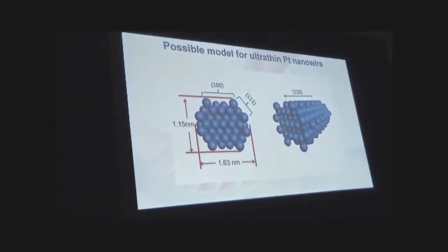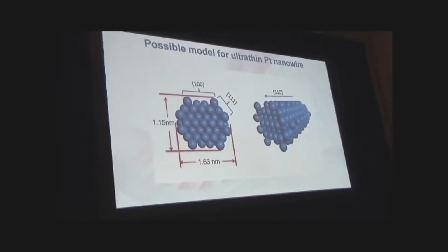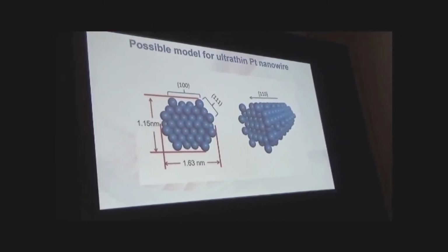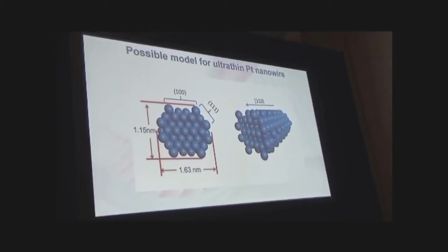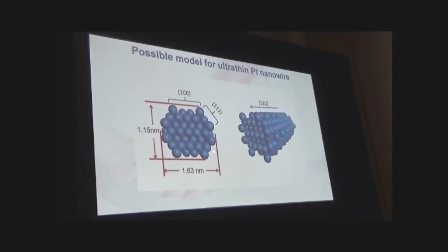Here is the model of the ultrathin Pt nanowire. Because, experimentally, the diameter of the Pt nanowire is about 1 nm, we can construct a reliable model. If you synthesize a nanowire of maybe 5 to 10 nanometers, we cannot construct such a reliable model because it's too big. But in our case, we can construct a reliable model for this one.